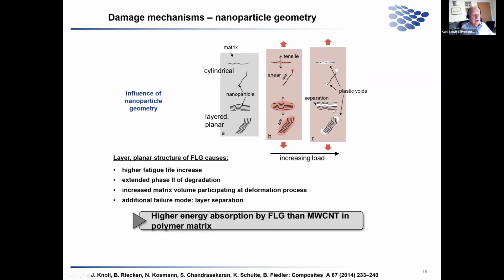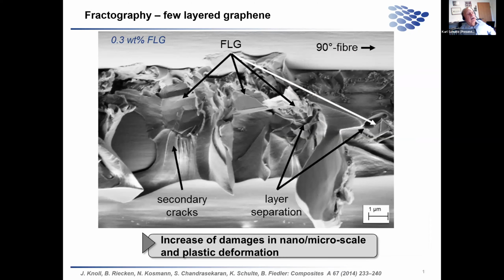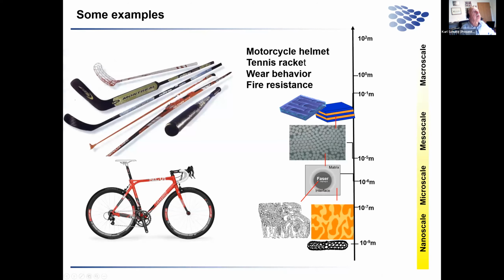So you have inside a lot of cracks. And if you have these cracks, it means at each crack you have a reduction of the stress intensity factor, which gives you a better performance in damage development. That is shown here with the fibers, and here you see the few-layer graphene particles, forming between more cracks. That is the result of why we have an improvement.